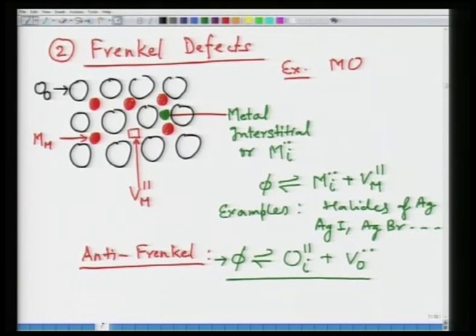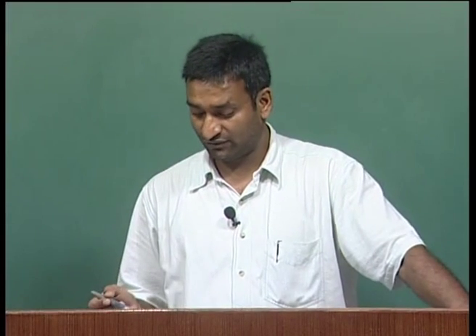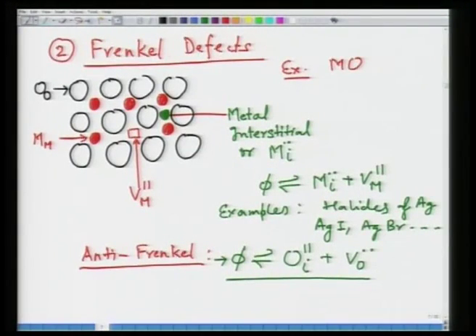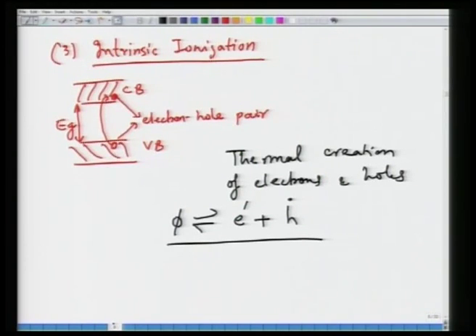And another kind of important defect is Frenkel defect. Frenkel defect is formation of a metal interstitial coupled with formation of a complementary metal vacancy, or in case of anti-Frenkel, it is formation of oxygen interstitial complemented by an oxygen vacancy. So these are the two most common defects that occur in stoichiometric solids. And third is intrinsic ionization, which is nothing but excitation of electrons from the valence band to conduction band, giving rise to an electron hole pair. And this can occur in any material.